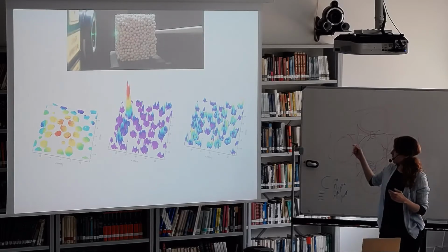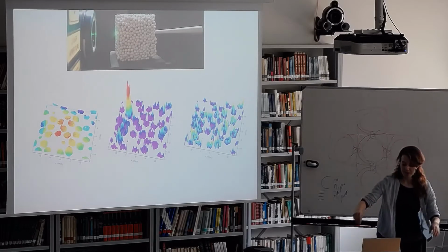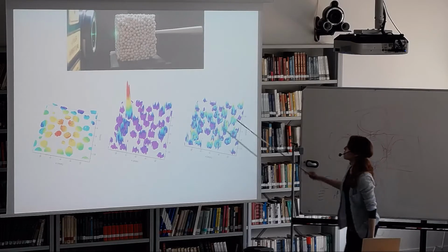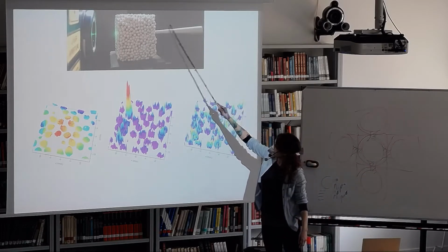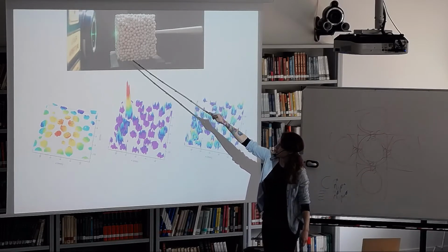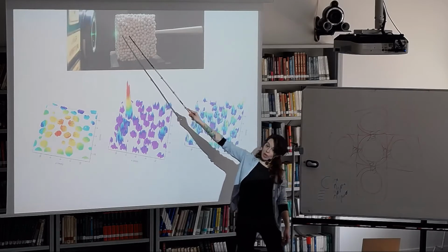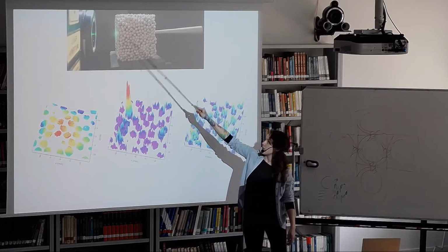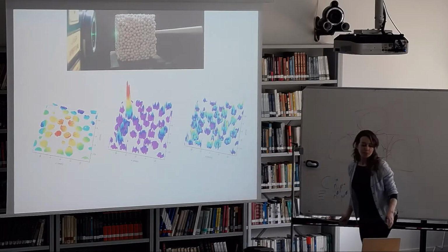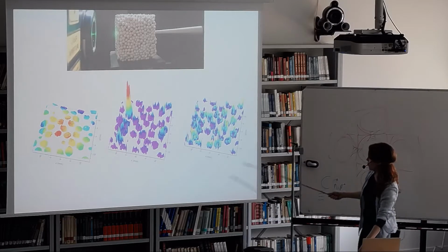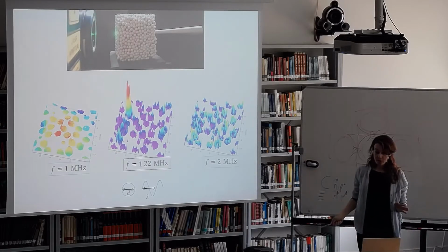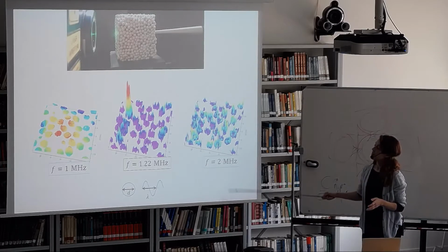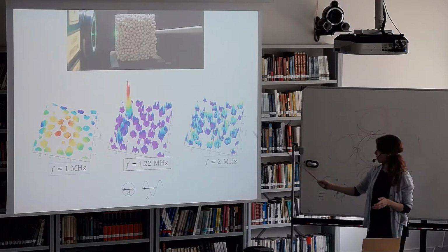So the diagrams here are essentially acoustic waves inside the samples measured at the face of one of these cubes. Essentially, we come in with a little probe here, send acoustic waves in. They essentially kind of fill the sample, and then here we have a laser interferometer, which we use to scan the surface of the cube. So these diagrams are different because they're measured for different frequencies of the waves. They range from low frequency to higher frequencies.